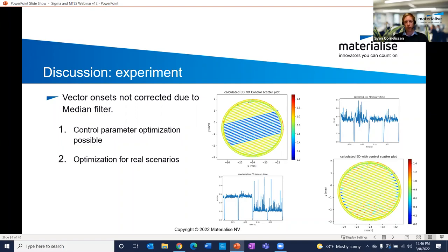And as a consequence of that, I think, and that's what happens in the nominal regions, the control loop is a bit too aggressive for the nominal regions. So in the nominal regions, you can see it best if you compare the nominal regions in the reference experiment to the nominal regions in the control experiment. You can see that in the control experiment, they become a bit more noisy, right? So in other words, our control is actually making the energy density a little bit less stable, I would say. And so again, this is a consequence of how we